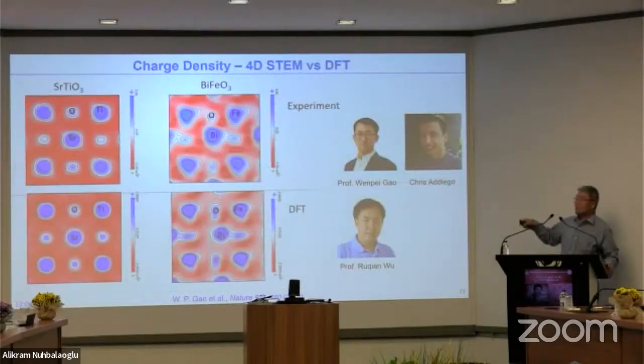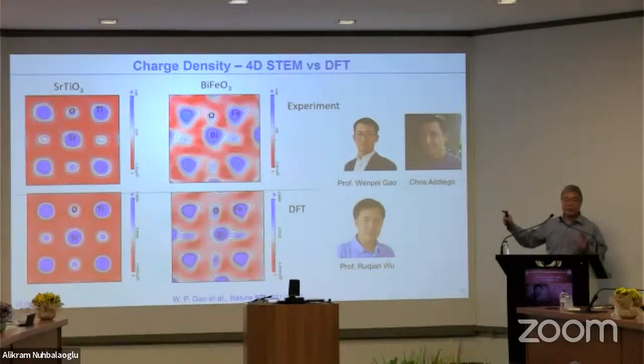But let's just compare the experimentally obtained charge density in these two different materials. One is ferroelectric, the other is not. With first principles calculations, DFT can also get charge density, and for both of these two materials you can see they match very well.